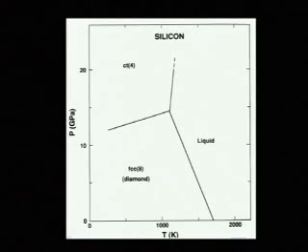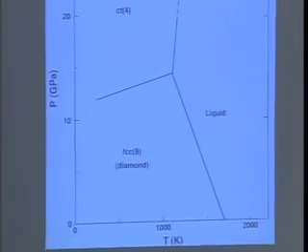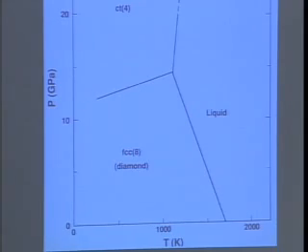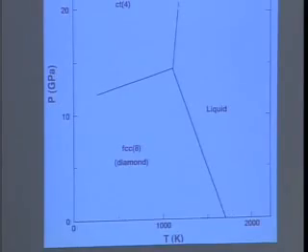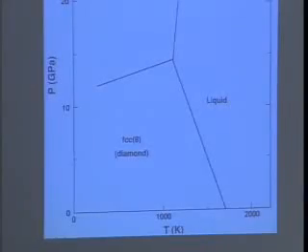There are other systems for which the same happens. Here's silicon. Here's the phase diagram for silicon, pressure versus temperature. You see down here, it's the diamond cubic structure, an FCC lattice. And there's the melting point of silicon. We go to the liquid, and it's got more nearest neighbors. How many nearest neighbors does the solid have? Its sp3 hybrid has 4 nearest neighbors. Most liquids have about 6 nearest neighbors. So when you have these open structures like silicon, germanium, the silicate glasses, and ice, you actually go to a more condensed system when you first liquefy.